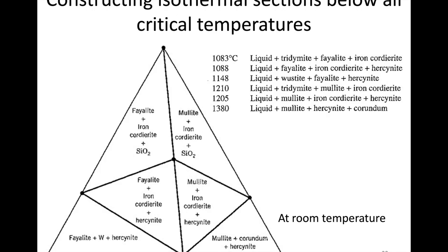If we keep going down in temperature and want to construct isothermal sections below the critical temperatures of all these reactions — from 1380 all the way down to 1083 where this reaction occurs — so basically at 1000 degrees or less for this system, we would expect to see all solid, no liquid at all. And the interesting and useful thing here is that this is exactly the same as the compatibility triangles. The compatibility triangles are basically the isothermal section below all the critical temperatures.